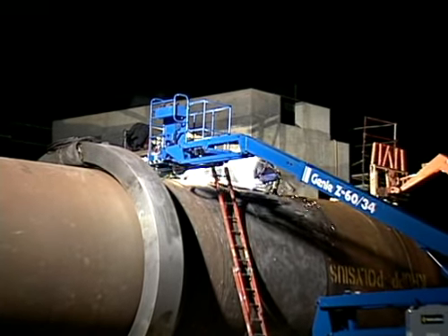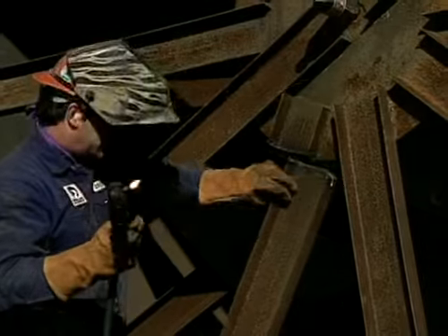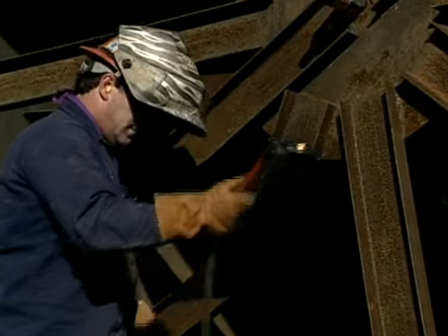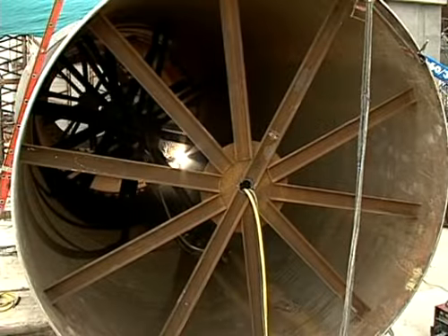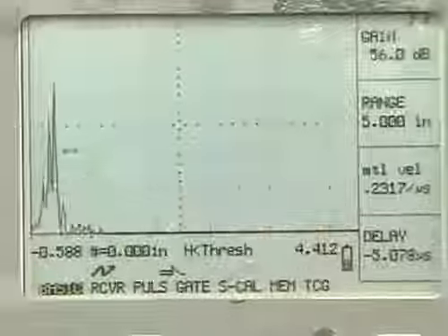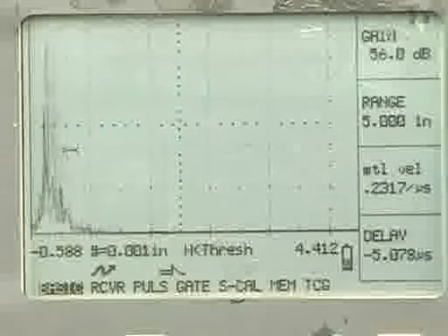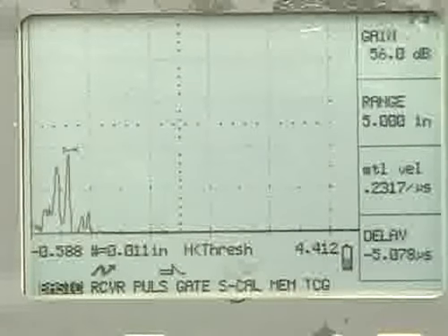Once the outside of the joint is complete, the activity shifts to the inside. First, all of the fit-up hardware is removed. Then the initial root pass that was laid in from the outside is removed from the inside of the shell using a carbon rod air arc, a process referred to as back gouging. This is to remove the inclusions and imperfections that it contains. Once removed, the joint is ground clean and filled. As always, the quality of this final shell joint is verified by non-destructive ultrasonic testing.